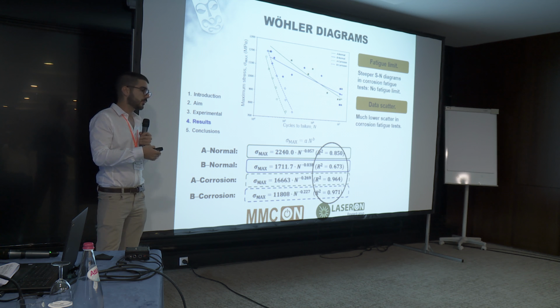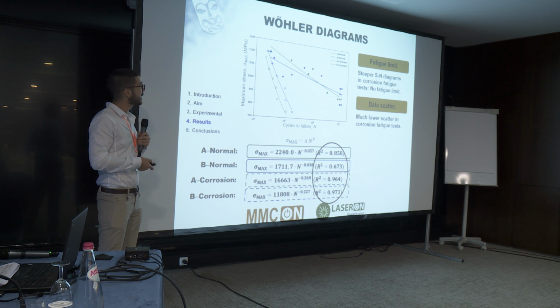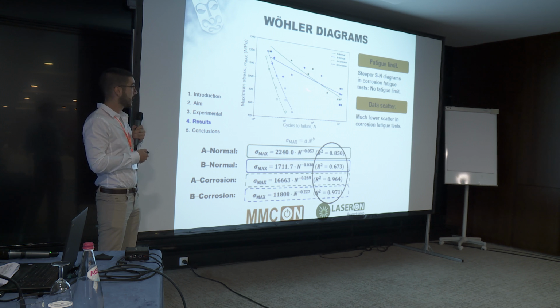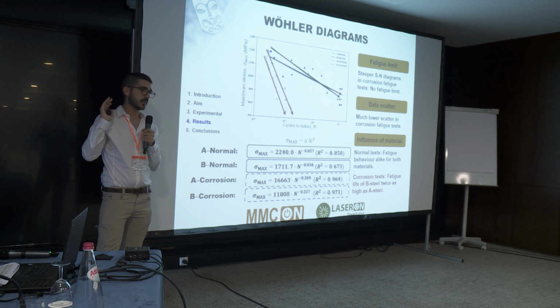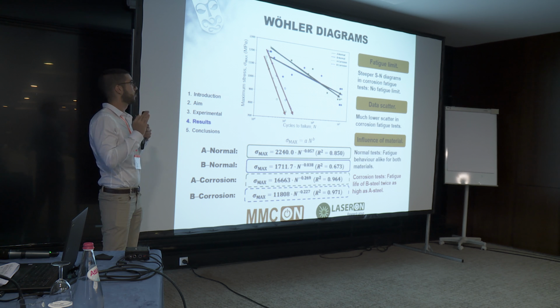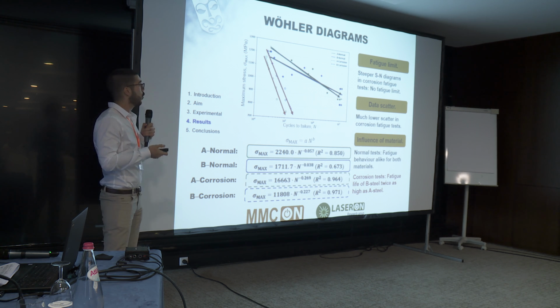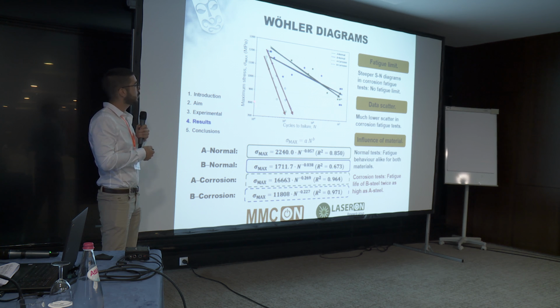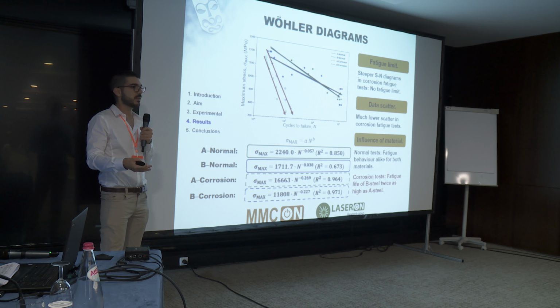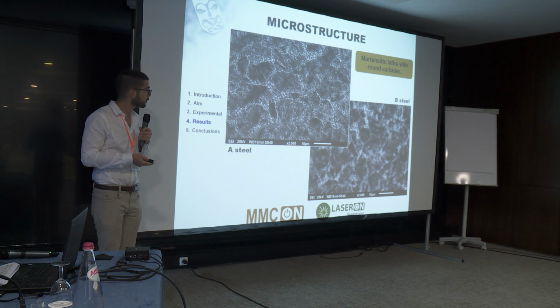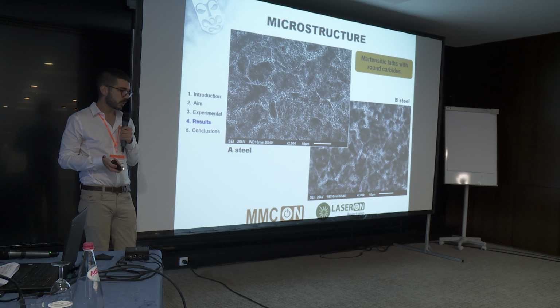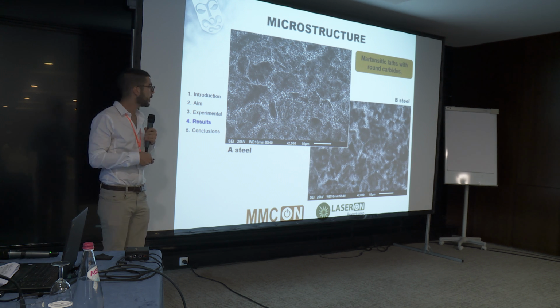If we look at the coefficients of determination of these curves, we can see that data is much more scattered in normal fatigue tests than in corrosion fatigue tests. And what's interesting is that under normal fatigue tests, the Wöhler diagrams were quite similar, whereas there's a statistical difference between both steels in the corrosion fatigue tests. Actually, the B steel presented, here the logarithmic scale is tricky, twice the fatigue life that A steel presented. So we analyzed the microstructures of both steels through SEM images.